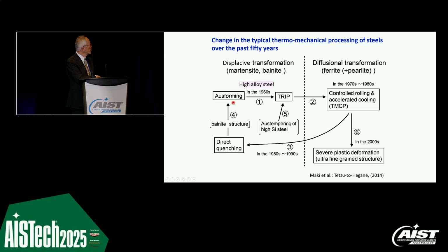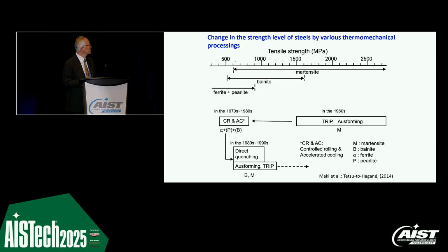Ausforming and TRIP. So we try to increase their strengths, particularly for sheet steel application. So we started from high alloy for ausforming and TRIP and low alloy for microalloy HSLA. Then again we go back to the low alloy steel for applying this kind of thermomechanical processing. Strength definitely changes, of course. First we have very high strength, over 2 gigapascal. Then we go to the lower strength product for diffusion transformation. Then we again go back to the higher strength now.